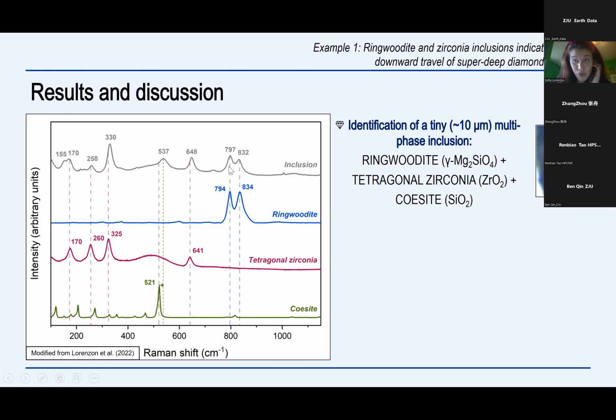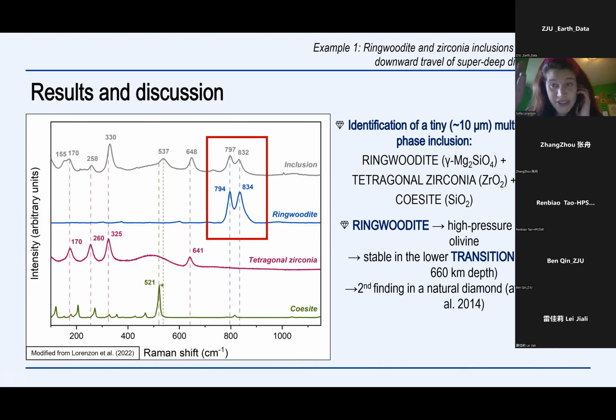Ringwoodite, as some of you probably know, is a high-pressure polymorph of olivine. Olivine is a magnesium and iron silicate, and is the major mineral component of the upper Earth's mantle. Ringwoodite is the polymorph of this mineral stable in the lower part of the transition zone, at depths between about 525 and 660 kilometers. Probably most of you know ringwoodite because, according to experiments, it is the major host of water in our Earth's mantle. In our case, this ringwoodite was also only the second finding of this mineral phase within a natural diamond, after the study of Pearson et al. in 2014.